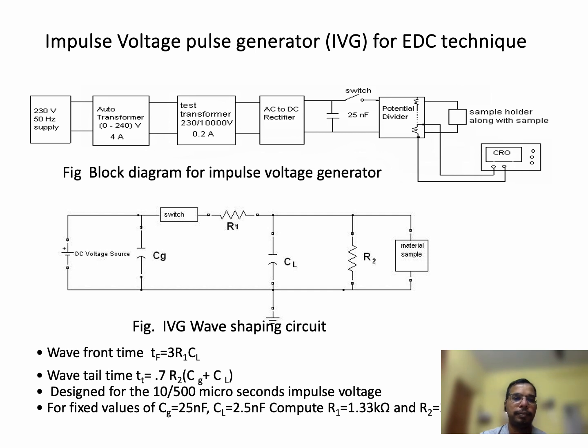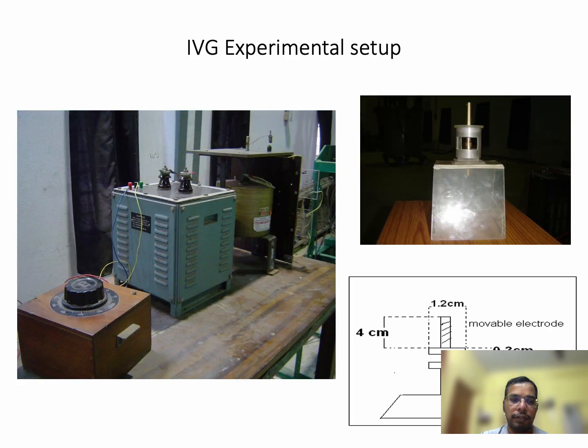By varying R1 and CL, we can vary the wavefront time, that is the rising time of the impulse voltage. Similarly, the wave tail time is computed from the generator capacitor and the loading capacitor. This circuit is designed for a 10 by 500 microseconds impulse voltage. We have an existing generating capacity of 25 nanofarad. We computed the other resistors and capacitors, and then employed nearby values of those resistors and capacitors. Here you can see our built circuit, and that is used for the sample testing.